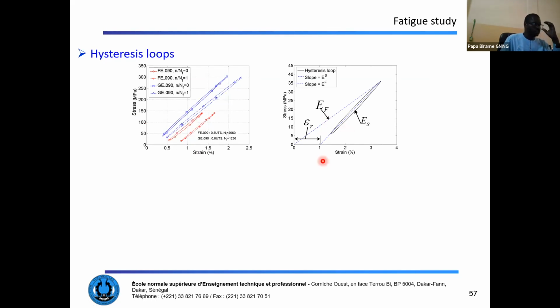So it is interesting to focus on 4 parameters during the fatigue loading, which are the secant modulus, the plastic strain, the fatigue modulus, and the size of the hysteresis loop, which corresponds to the energy dissipated throughout the cycle. As we can see here in the left picture, for example, for the glass, the slope of the hysteresis loop is diminishing from the beginning to the last cycle.